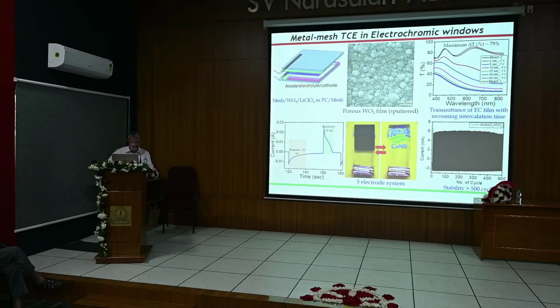And we have taken it further, trying to use these functional glasses in electrochromic smart windows. Not only that, can we make these windows work like a battery? Can they store charges as well? So this has been addressed through another project. You can see here the functional glasses enclosing the electrolyte system. And in this case, it is a porous tungsten oxide system. And with time, after application of the voltage, within a minute you can see the transparency drops. And that is visibly seen here, right?